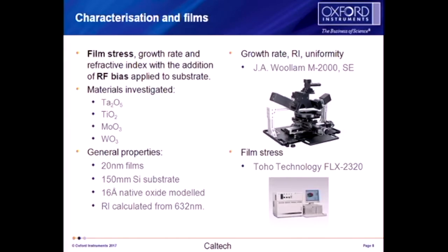There is, though, fundamentally some limits to that. The film thickness here is only 20 nanometers. Ideally, you would go 2, 3, 4 times thicker than that to get a really solid result. But this is ALD, and thin films are where we work. So do you have a feeling for how much uncertainty is in your data, given that? I mean, I would be concerned. Yes. Needs to be run a lot more times. Ideally thicker films to give us greater confidence in the results.